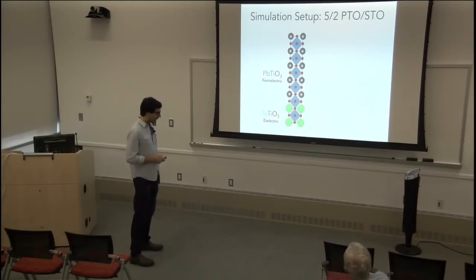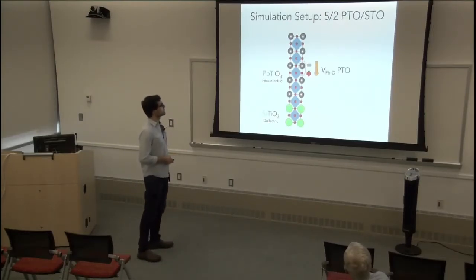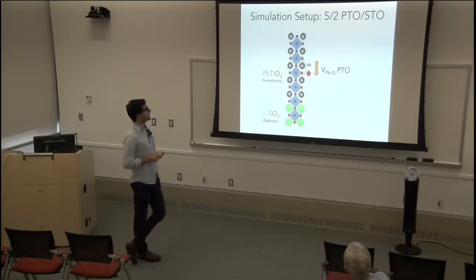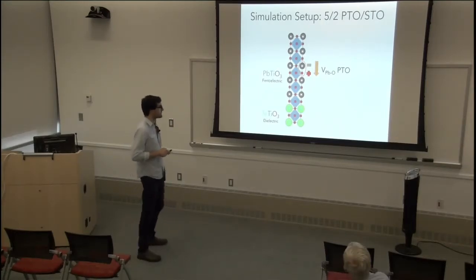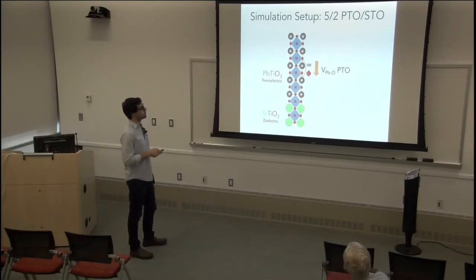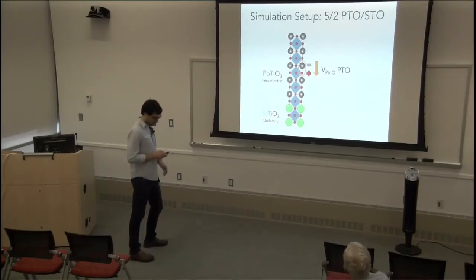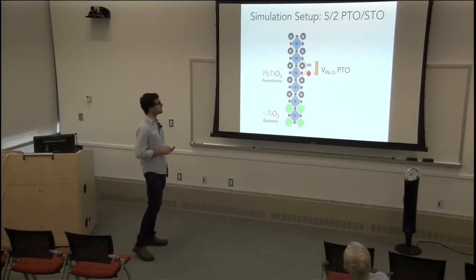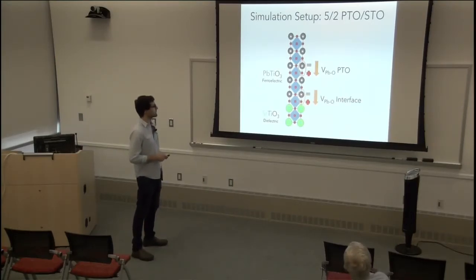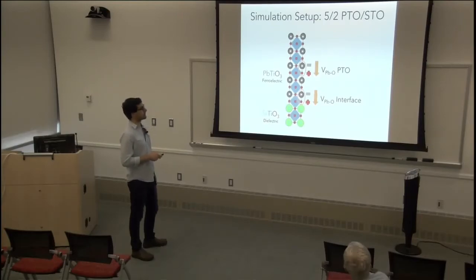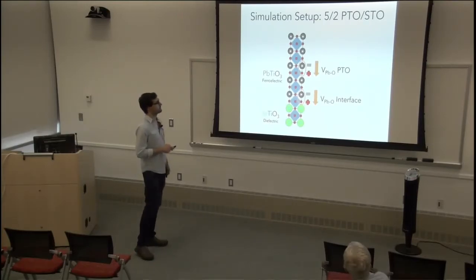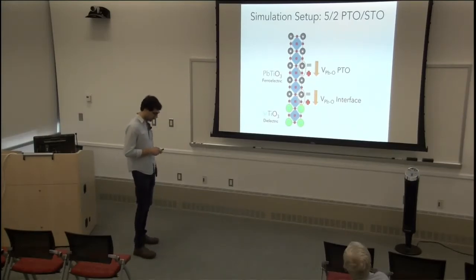The way we do it is we introduce defects. We take out this lead cation, so you're left with a negative vacancy, and remove this anion, and we're left with a positive vacancy. This negative charge and positive charge give you a dipole moment in the lead titanate. Likewise, another unique location where we can have these dipole moments through divacancies is at the interface. And clearly, because dipole moments will couple with the polarization, we expect these perturbations to lead to an asymmetric domain wall.